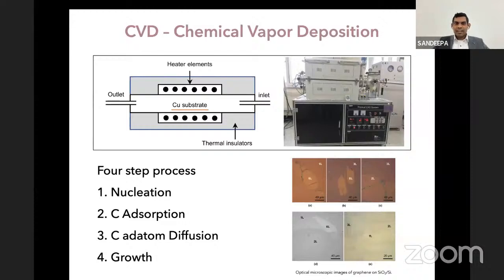And we let it nucleate. This carbon and this catalyst surface has one important function. It adsorbs materials, and after that, the adsorbed material will diffuse to the nuclei. That's the nucleation and growth mechanism in the CVD technique. But in some situations, we use very low pressures. That kind of technique we call low pressure CVD. The other option is atmospheric pressure conditions. But if you think about high quality graphene, low pressure CVD is the much better option.